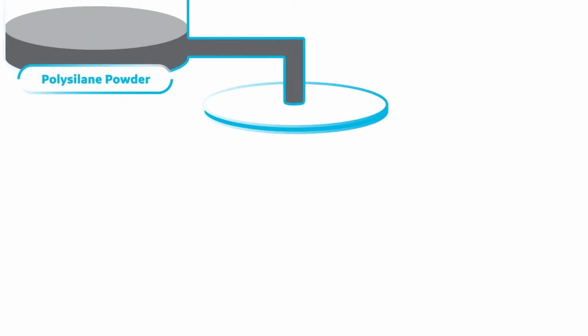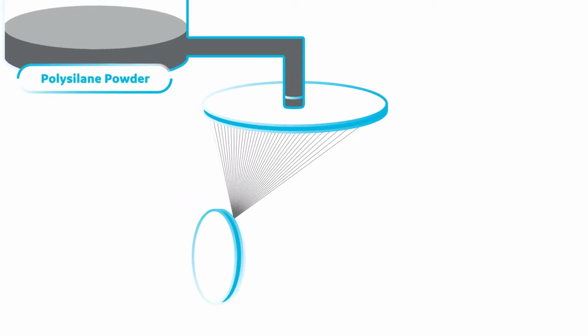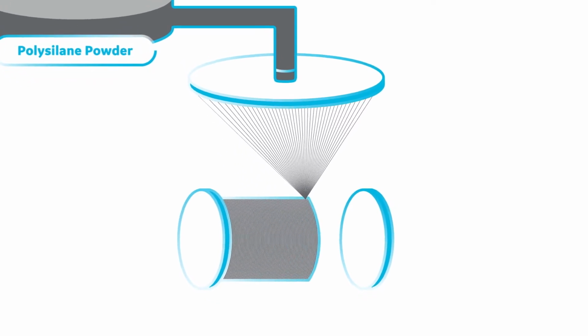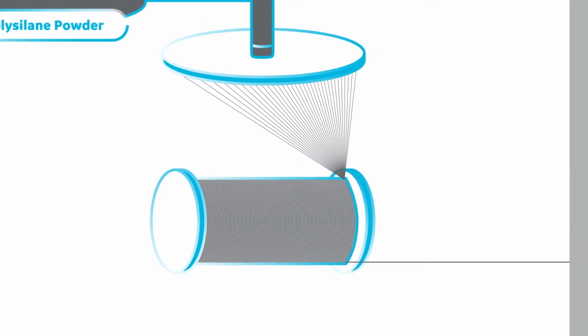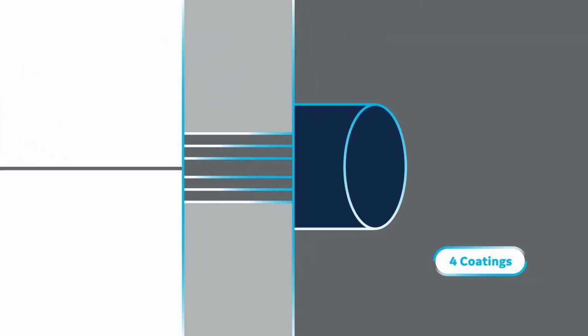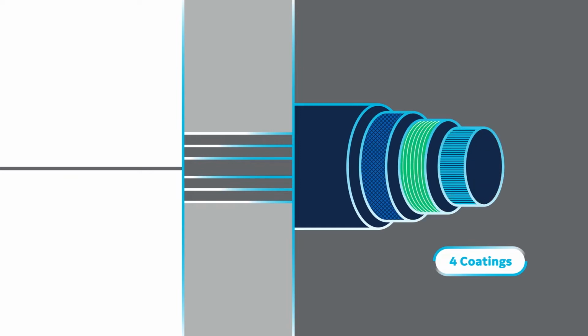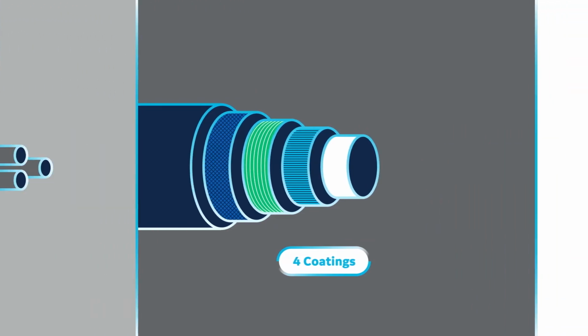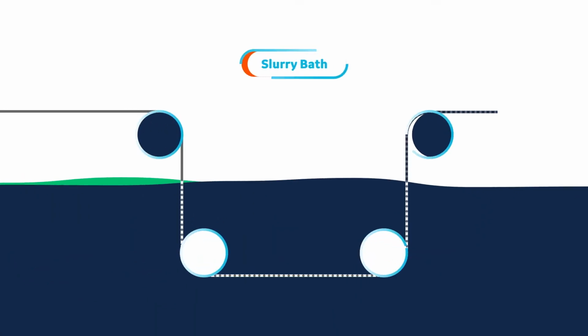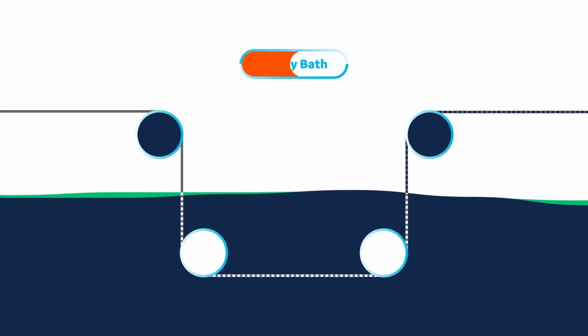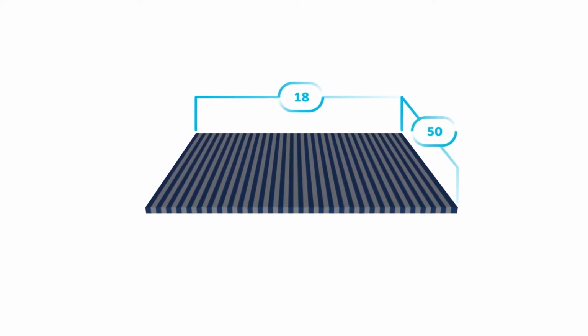It all starts here with polysilane powder. By melting this powder, we're able to spin, cure, and heat treat it into a high-strength, corrosion-resistant, low-density silicon carbide fiber, each one only 1/5 the diameter of a human hair. The finished strands then have 4 proprietary coatings applied, coatings that enhance the fiber and build its strength and creep resistance. Next, the treated fiber is passed through a slurry of solvents, binders, and plasticizers, and spooled around a wet drum, transforming these fibers into a workable tape, large sheets of unidirectional fiber.